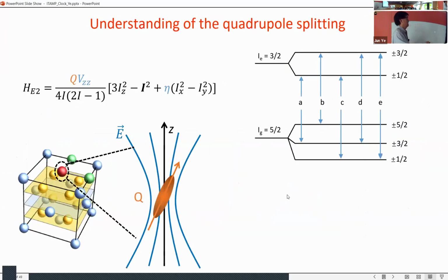From that, you can immediately plug into this Hamiltonian that governs the interaction of the nuclear quadrupole moment with the electric field gradient inside the crystal. So you have this cylindrically symmetric, incompressible liquid drop model of the nuclear volume, and it's got to carry the quadrupole moment. And you subject this to an electric field gradient with the so-called anisotropy factor eta, describing the difference of the gradients between the x direction and y direction, with the quantization axis defined in the z direction.